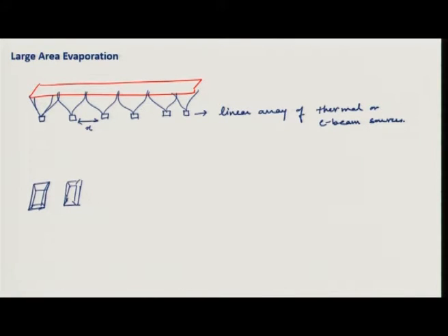And a wire of the material that you want to deposit is continuously fed into this, and there is somewhere a big spool of wire, and using some pull mechanism you can feed this wire continuously into this boat. Okay. And this boat is kept heated at a certain temperature, so that as soon as this wire touches the boat, it melts, it evaporates, and it creates a small pool of molten material, and from where it goes to vapor phase.